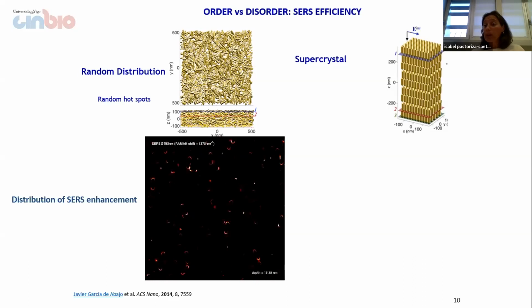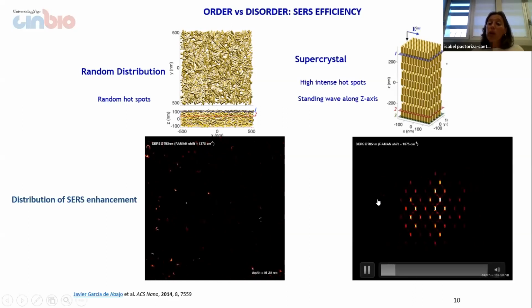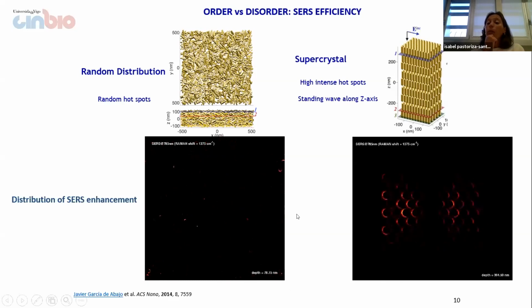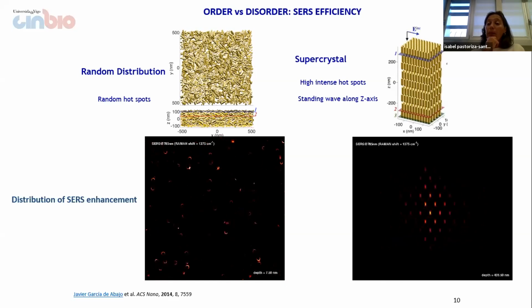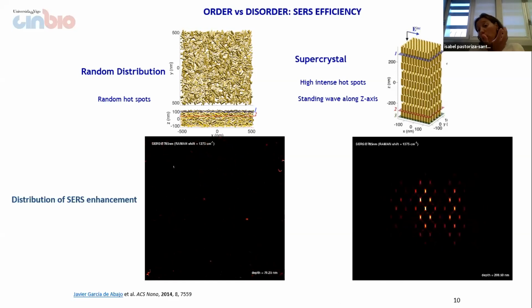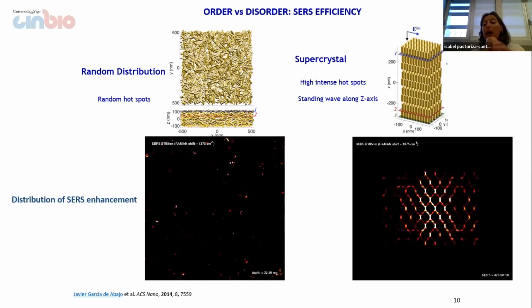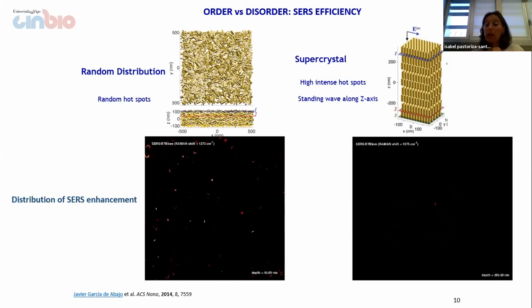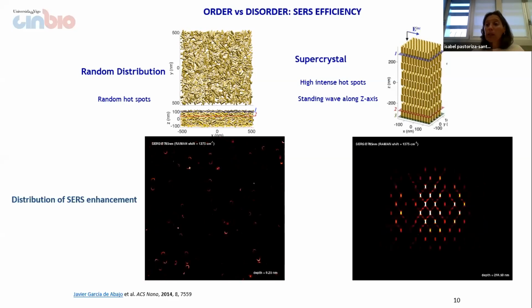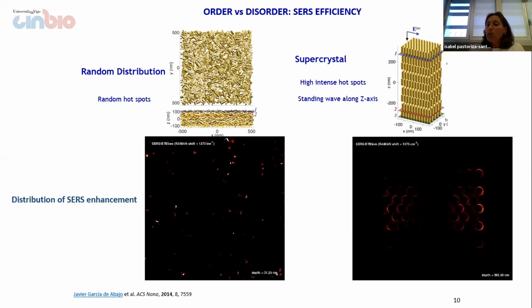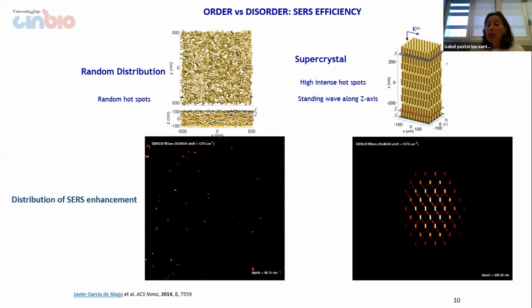Nevertheless, the situation in the case of a supercrystal is completely different. So in that case, what they observe is that when they are illuminated with light, there are propagation modes that form standing waves, and these standing waves form areas with really strong hot spots or a really strong SERS signal, and these areas appear at different resonant depths in the supercrystals, and there is not really a decay in the SERS signal when we move inside of the supercrystal. Therefore, for SERS sensing it is very nice to try to fabricate plasmonic supercrystals.